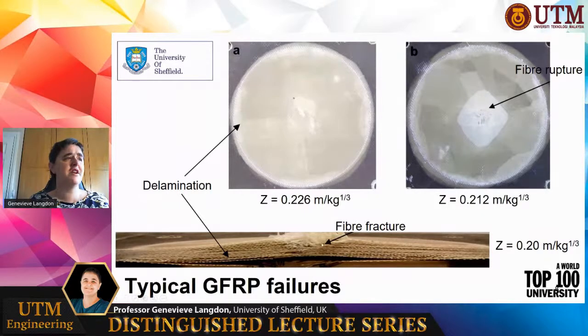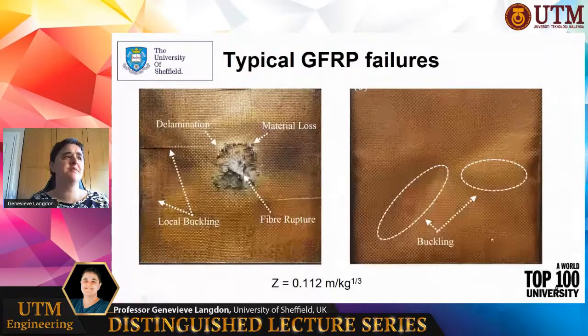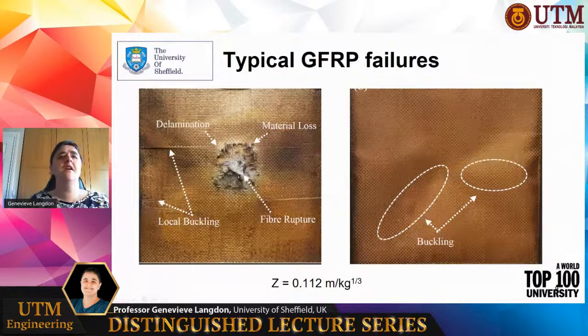So the material gets to a point where its capacity to deform is gone, and it breaks as the fibers rupture. And eventually, if you keep loading this type of material, it will rupture all the way through the cross section, and then it will just let the explosion through, which can be very devastating if you're using that as a protective material. Here are some other typical photographs of failures.